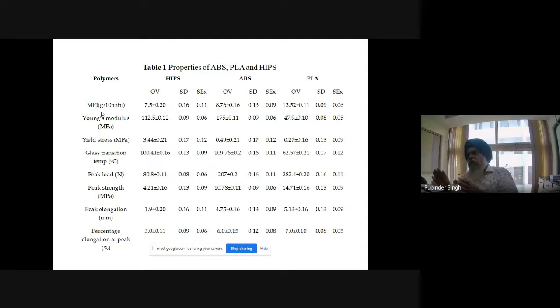If the MFI is more, I can make a thin section. If the MFI is less, I cannot make a thin section, right? So basically, if you see the difference in the observed values, for HIPS it was 7.5, for ABS it was 8.7, and for the third case it was 13.52. That means if I am working at the same temperature condition for printing the substrate of HIPS or ABS or PLA, right?